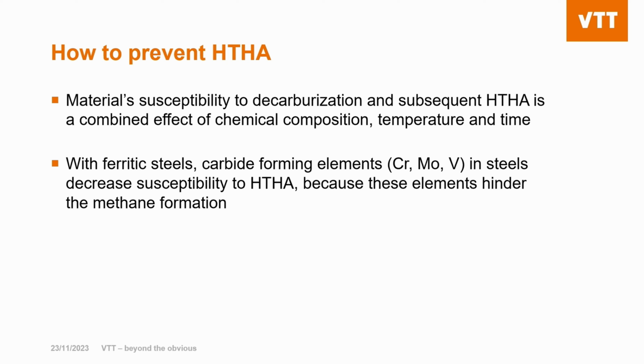Now, materials' susceptibility to decarburization and subsequent high-temperature hydrogen attack is a combined effect of materials' chemical composition, process temperature, and time. With ferritic steels, these carbide-forming elements such as chromium, molybdenum, and vanadium in these steels decrease the susceptibility to high-temperature hydrogen attack because these elements hinder the methane formation.